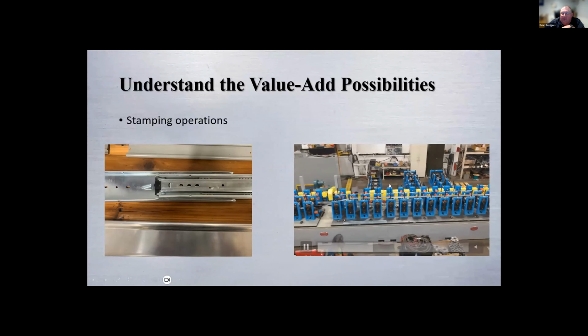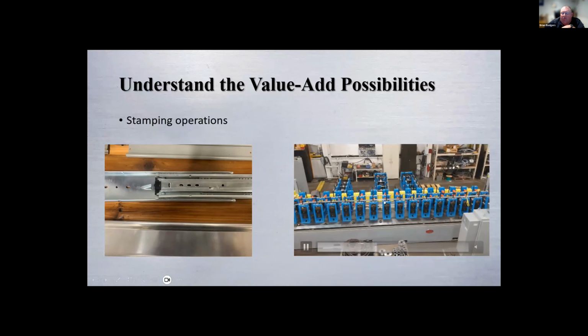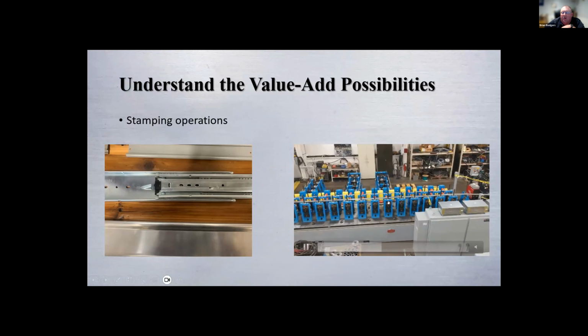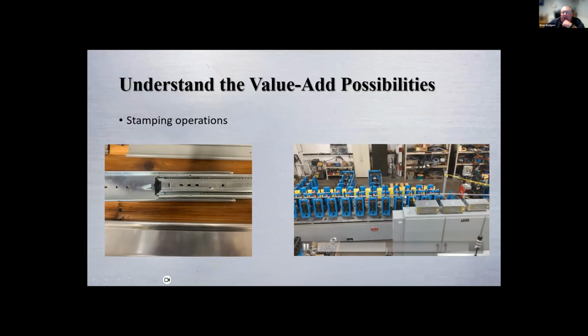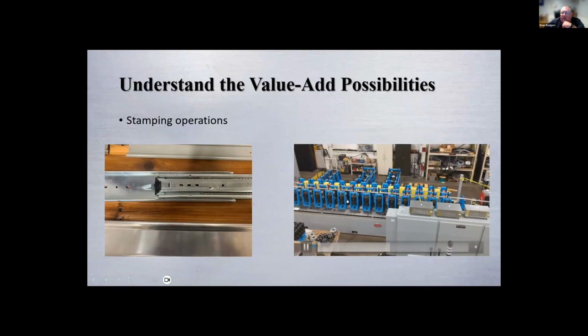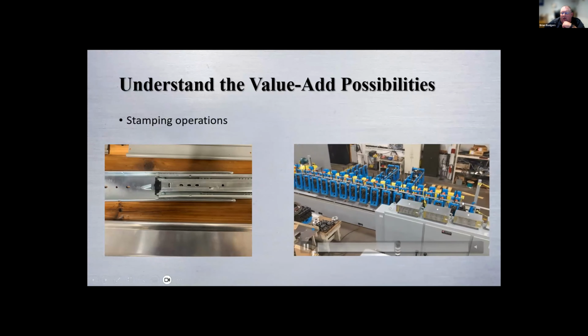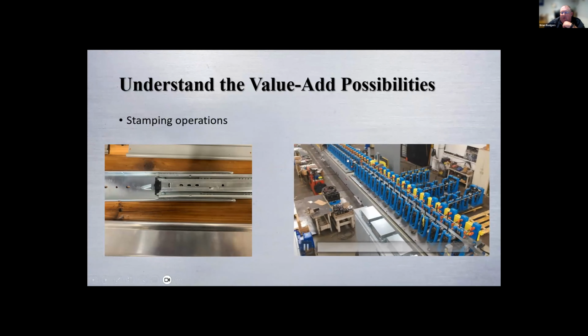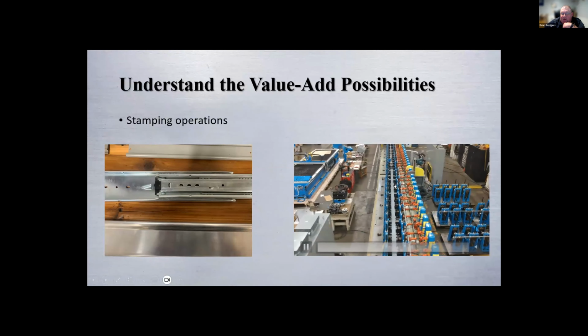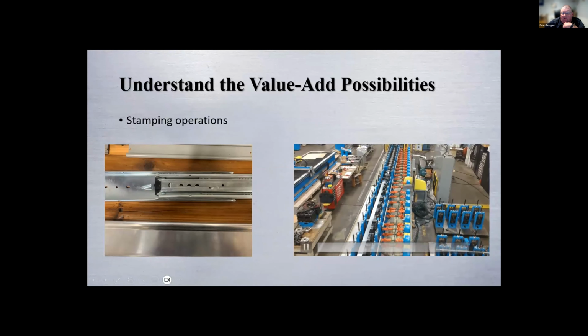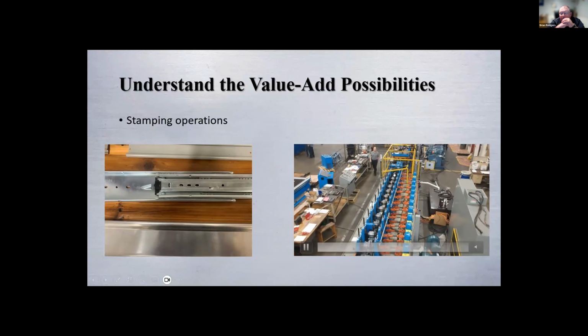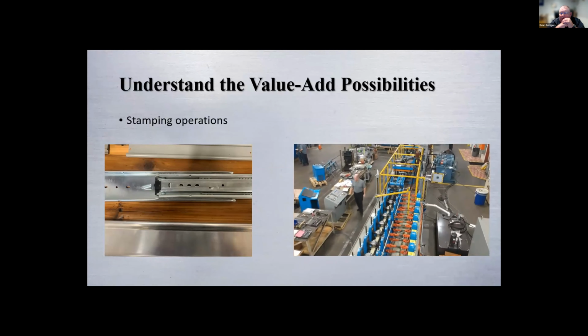We call these rafts that are sitting here on the floor. And these rafts would come in exchange with these to run the 3 different profiles. It just so happens on this one, we're not using the beginning of the roll former. So we're just running the coil over top, and then we're dropping the coil down into the forming stations here at the split of the roll former. And then as you can see, you see the strip, you see the tooling, and then the part is going through, it's being formed. It comes into a straightening process, and then it comes into the presses.